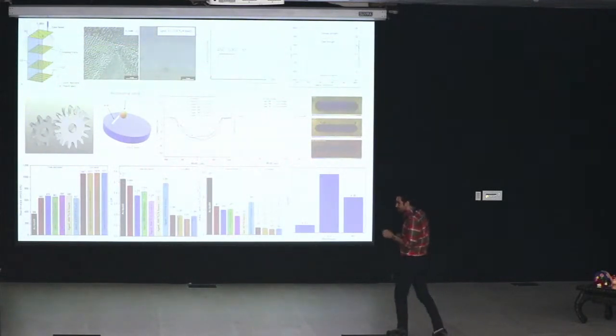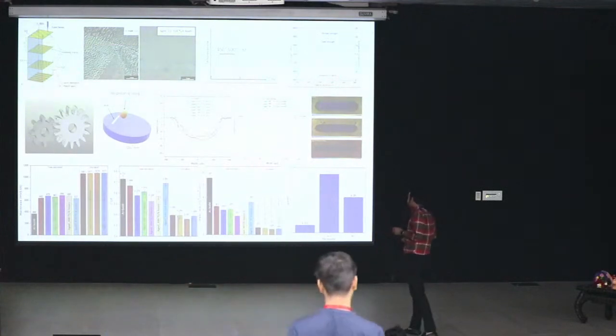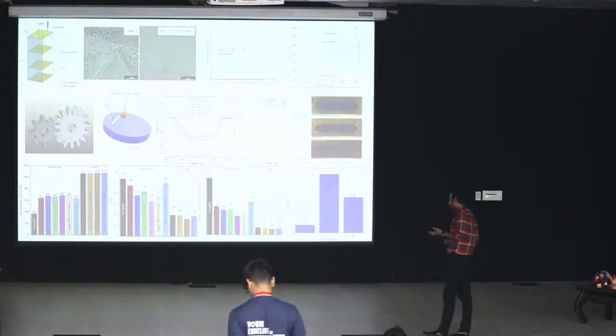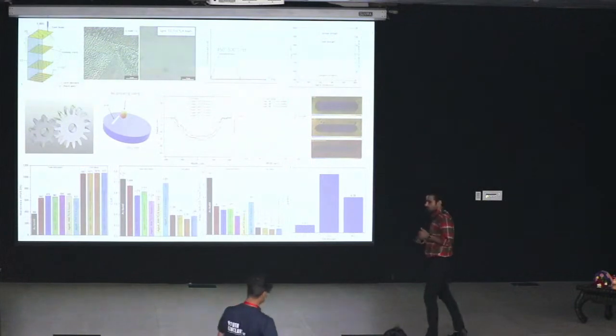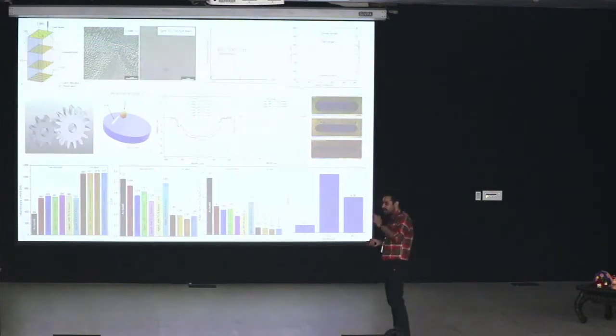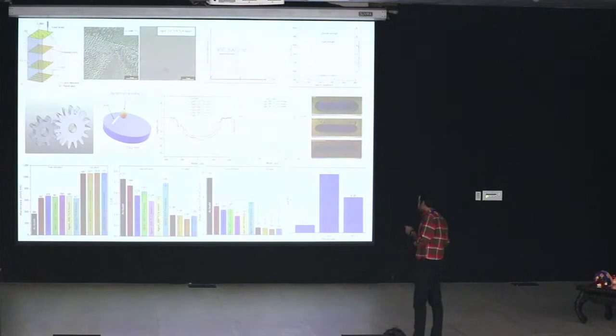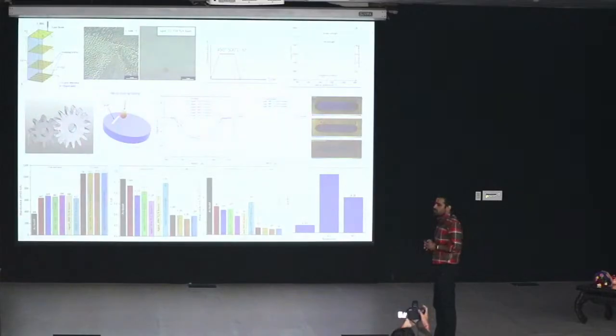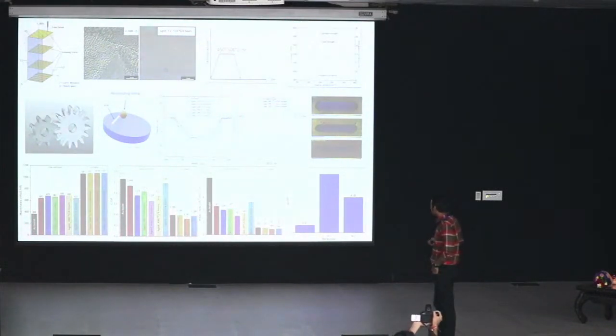So now, one thing is clear that instead of using the as-built specimen, we will use the nitrided specimen, that is as-built plus nitrided condition or aged plus nitrided condition. But we need to choose one of these two conditions. So we will eliminate the aged plus nitrided condition because for the aging process, we need to further input electricity in terms of kilowatt hours, and that will cause the production of CO2 gases, SO2 gases, and NOx that can directly harm our environment.